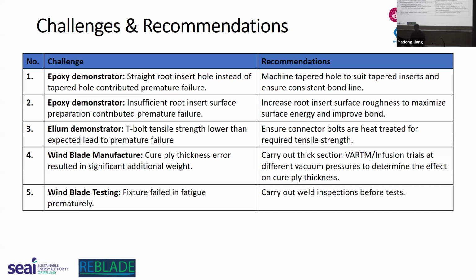Then the wind blade manufacturing. So this is another significant learning curve. When you're infusing with two different materials, depending on the process, you may have to infuse at full vacuum for epoxy, which means you're infusing at 1,000 millibars of vacuum pressure. But for Elium, it's recommended to infuse at 750 millibars. So it's 3/4 of a full vacuum. That means the consolidation pressure is a lot lower. And yeah, so that meant that we